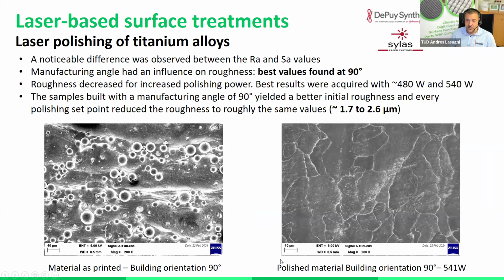This can also be seen here in these scanning electron micrograph images. So a typical initial structure with some waviness that is related to the different tracks that are produced by the manufacturing process, the typical powder that is attached to the melt pool, and then after the laser polishing process, we can observe very well the polished surface, and we even start to see the different grains that are related to the microstructure of our material. That means now we have our material that is polished.